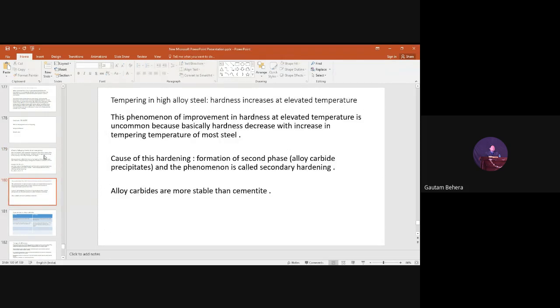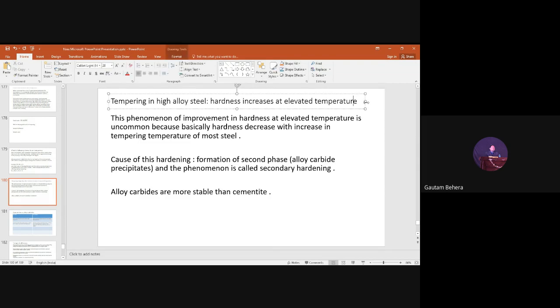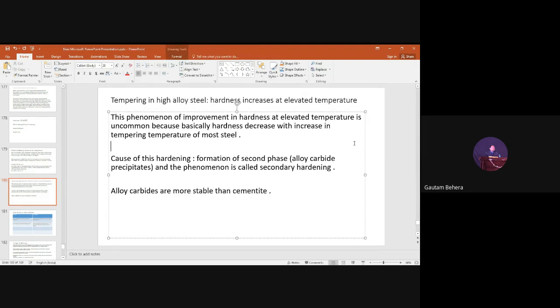Now you can see a very interesting thing I have written over here: tempering in high alloy steel. Suppose you are dealing with a steel containing a higher amount of alloying elements. What happens? Hardness increases at elevated temperature. You understood our objective is to improve the ductility, improve the toughness, or decrease the hardness, or decrease the brittleness of the steel. But this is just the opposite phenomenon. You are doing tempering of as-hardened steel, and the hardness is increasing. This is very interesting. How is it happening?